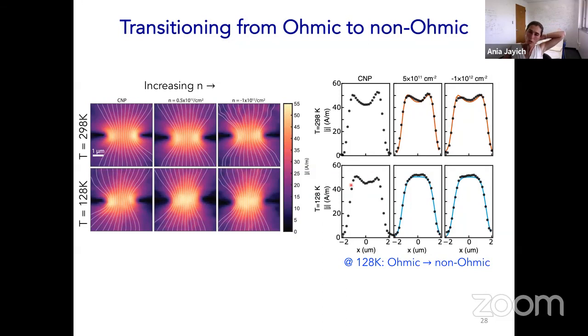So we've seen a transition from ohmic flow to non-ohmic flow as we go to lower temperature and away from charge neutrality. At charge neutrality, you still expect ohmic flow at low temperature because there's a fair amount of scattering, there's electron-hole recombination, not a lot of screening there.